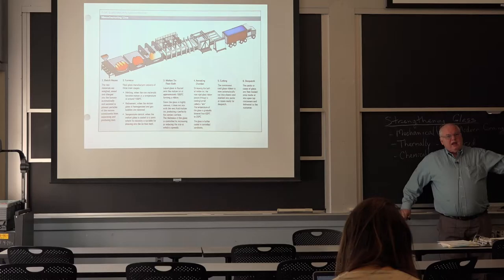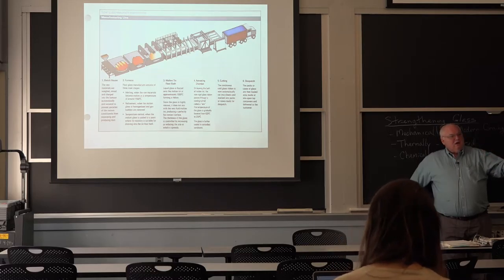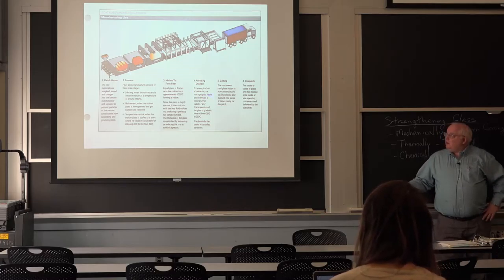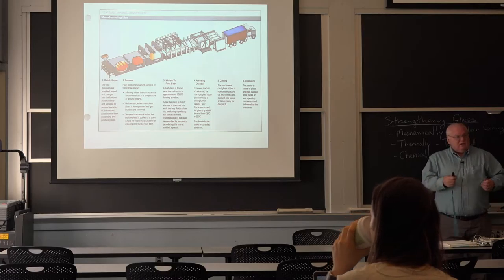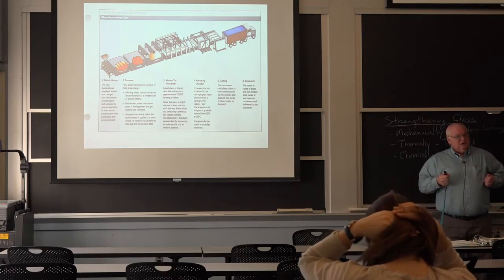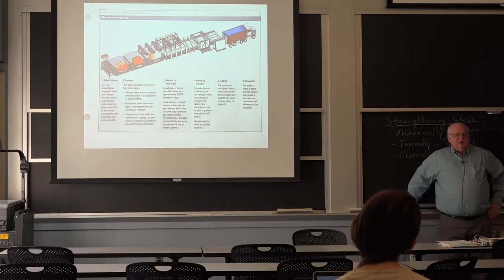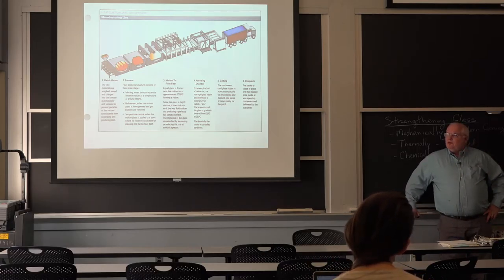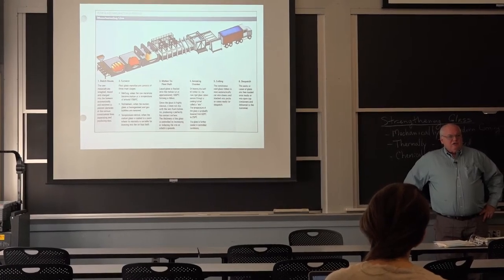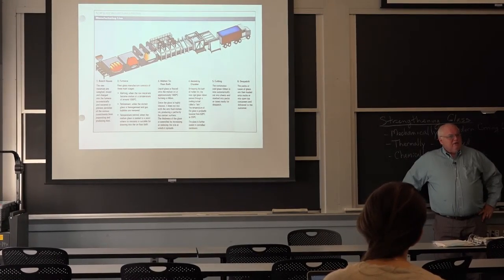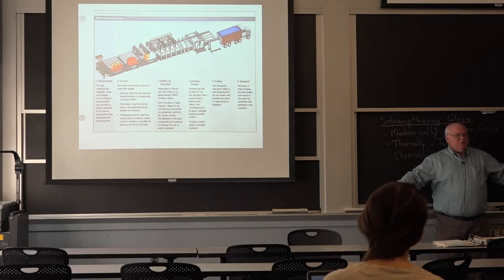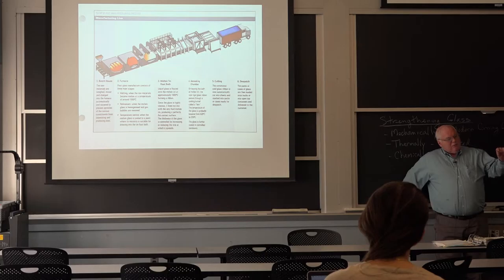And so they would pull the hot glass out onto this bath of hot molten tin, and the top surface would just be floating in the air. If they do this as a continuous process and run it along for about 20 or 30 feet as they're pulling it slowly out of the furnace, I've only been to a couple of float glass plants, but they're probably pulling 5 inches a minute or something like that. You're not pulling it out very fast, but it's a continuous process, and the whole thing might be 20 feet wide. You pull it out at the right amount, the right thickness. You can control your thickness within limits.